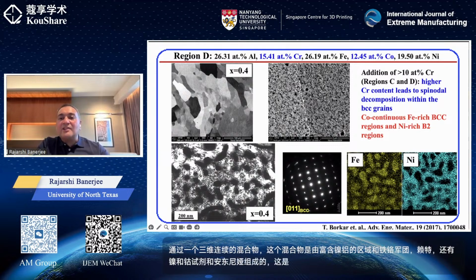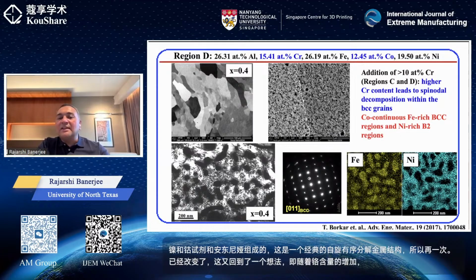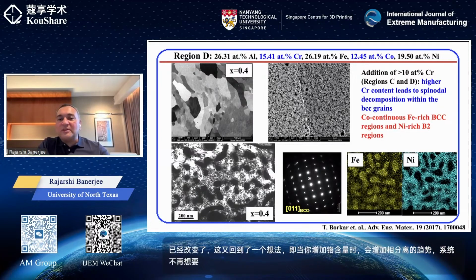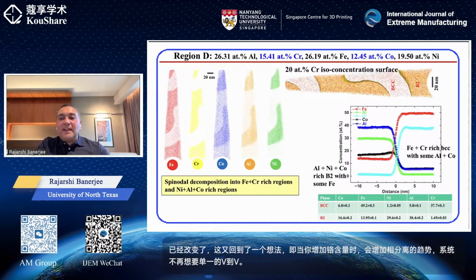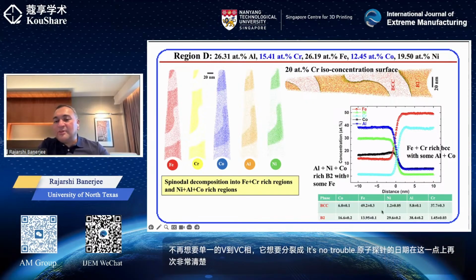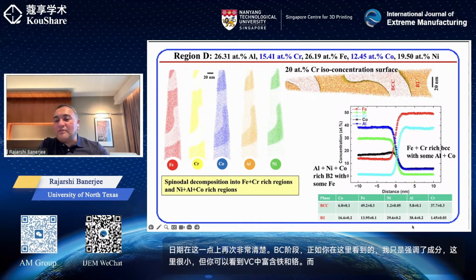So that again has changed. And this goes back to the idea that as you increase the chromium content, you increase the tendency for phase separation. The system no longer wants to be a single B2 or BCC phase. It wants to split up into two phases. The atom probe data again is very clear on this. The BCC phase, as you can see here, is heavily enriched in iron and chromium, whereas the B2 phase has a significant amount of nickel and aluminum, but also quite a bit of iron and cobalt still retained in there.